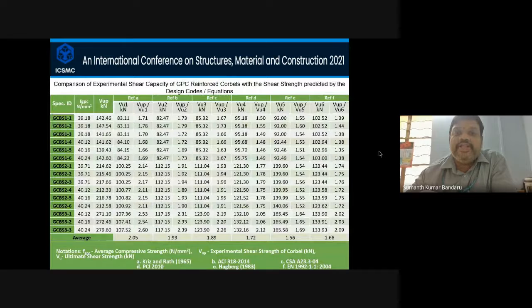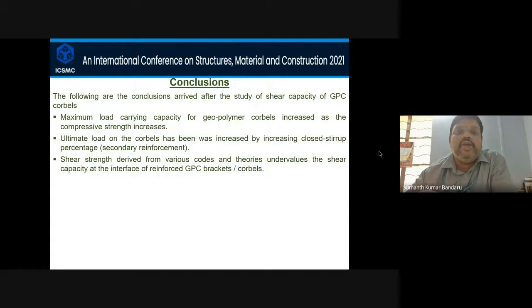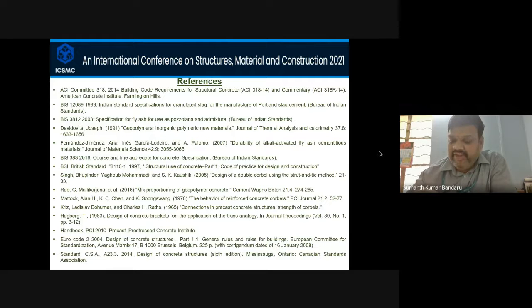This is the comparative statement of the different shear strengths predicted by design codes, where we can see that the average values are more than 1.5. We can conclude that the maximum load carrying capacity of geopolymer corbels increases as the compressive strength increases. Ultimate load on the corbels increased with increasing closed stirrup percentage, and the shear strength derived from the various codes and theories undervalues the shear capacity at the interface of reinforced GPC corbels and brackets. These are my references.